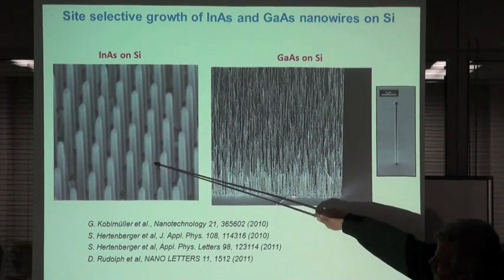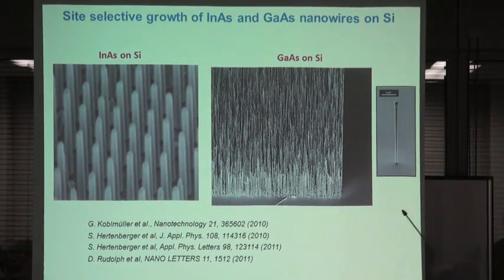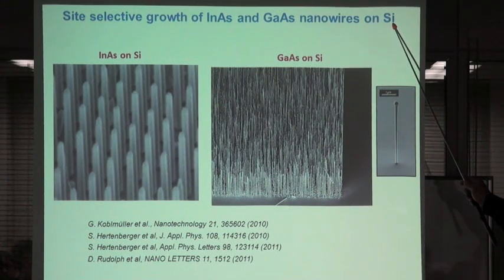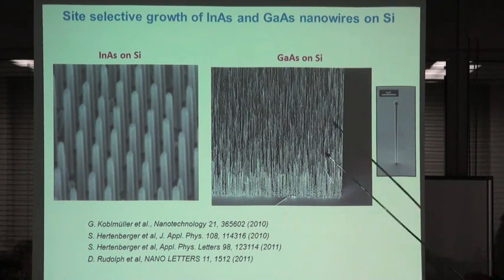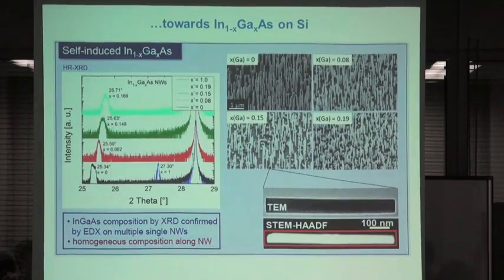We can also grow coaxial structures. We can overgrow them with the other doping or with heterostructures, with aluminium gallium arsenide, and we can embed quantum dots in such a system. But I talked about this 2 weeks ago at Komaba campus extensively, about these nanowires and electrical and optical properties. Here I just wanted to add it because it fits a little into my subject today, silicon, because we now grow these III-V nanowires on silicon, basically defect-free. So we can combine III-V with silicon, and also we can change doping and heterostructures, despite the large lattice mismatch, because these wires are so narrow.